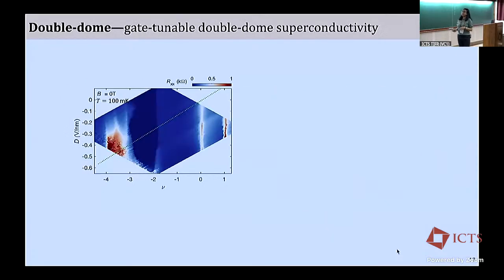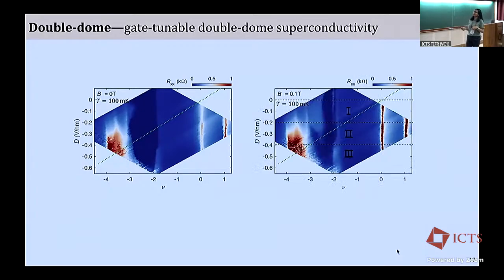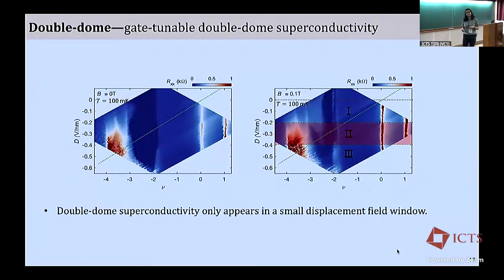And then the most interesting thing that we found: I told you that we are interested in tuning things, so we want to have some electric field dependence. Now you see that if I turn on a small magnetic field, here 100 millitesla, we start seeing that indeed the superconductivity has two domes in only a small window. It's a very small window where we see that, and this is not something very trivial for us. At least we found a knob. So this is what we want to stress.